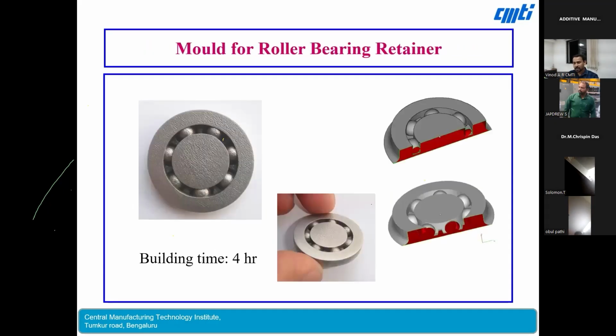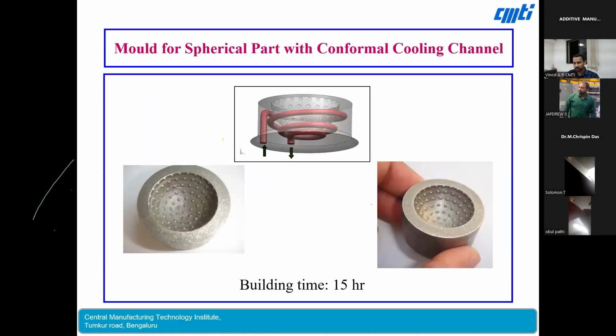You can see another interesting application. This is a mould for a roller bearing retainer ring, basically for plastic. For one of the industries, they wanted to make a retainer ring for ball bearings. The retainer ring has to be made of plastic. For making that plastic retainer ring, they need to make one mold. So this is the metallic mold. If you look at the CAD geometry, you can see there is an undercut at the bottom. By CNC, probably you can easily machine the top surface, but the bottom will be difficult to manufacture because of the undercut. If you want to manufacture by the conventional route, at least you have to split it into 2 halves. But here, without splitting, as a single part, it was fabricated within 4 hours using steel material.